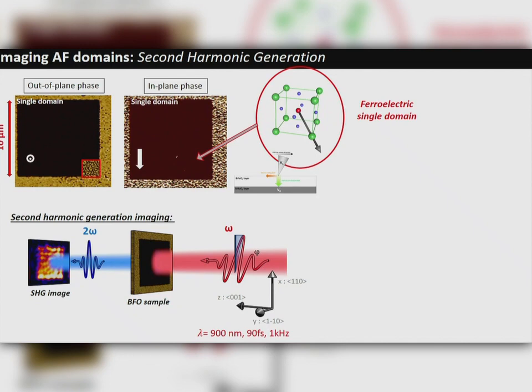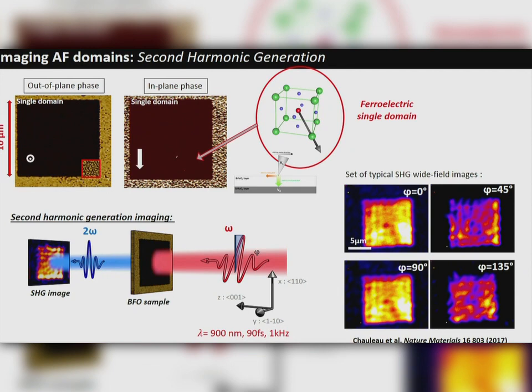So our laser, it's a kilohertz laser, about 90 femtoseconds. In this case, the light was at 900 nanometers. And these are the kind of raw image that we have. Then you can definitely see, this is for different kind of polarization direction. So basically, you can directly see the square we have written, but at some different polarization direction, you can see that there is a substructures.